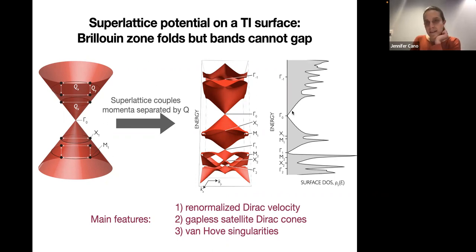But what happens now is that the density of states develops all these ripples, and these ripples can be traced exactly to what's called satellite cones, these different points in the energy spectrum where you see that there are new Dirac cones emerging. Those give you these dips in the density of states. And so if you can measure the density of states of this heterostructure in these dips, that would tell you something about the Fermi velocity of your material, and it would confirm that you've achieved that your potential is actually affecting the Dirac cone in the way that you expected.